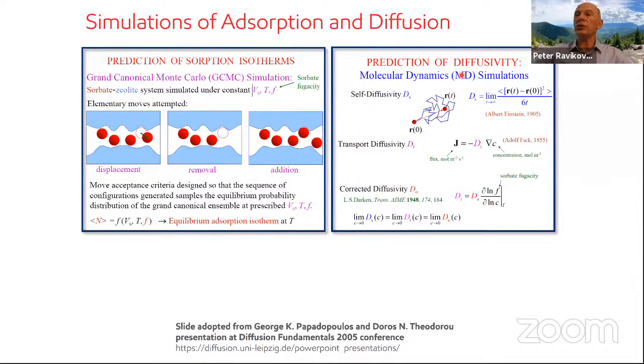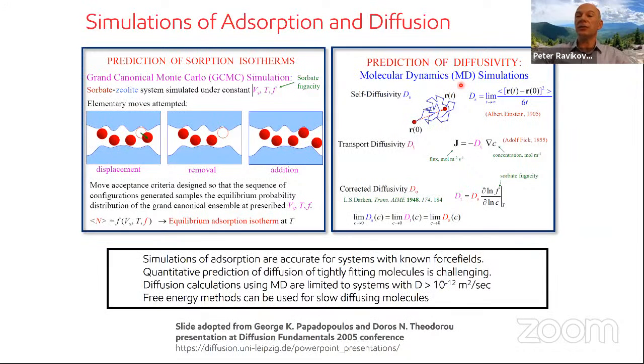It is more computationally expensive, but not terribly expensive. The problem, again, is availability of these force fields, but the biggest problem with molecular dynamics is that there is a range of diffusivities at about 10⁻¹² meters squared per second. If diffusivities are faster, then molecular dynamics can be used. If diffusivities are slower, then transition state or free energy methods can be used in order to calculate the free energy barrier and then calculate diffusion using transition state theory.